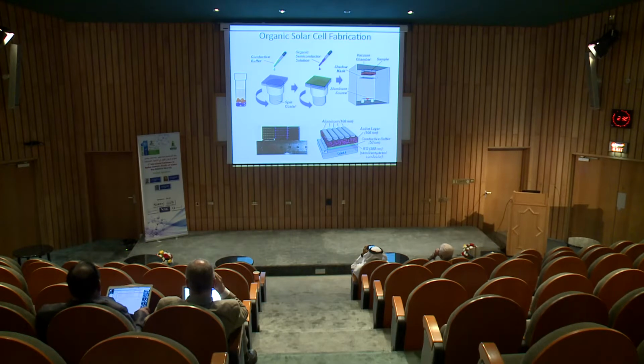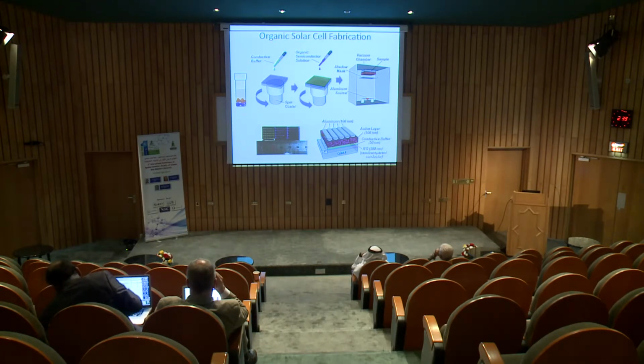After we deposit the organic semiconductor solution, we transfer our film into the vacuum chamber, where we thermally deposit the aluminum cathode. The device schematic drawing is shown at the bottom right, and on the bottom left is an actual photograph of organic solar cells prepared with different donor materials. You can see here we can change the color of the solar cell from green to blue to red, depending on the donor that we use.